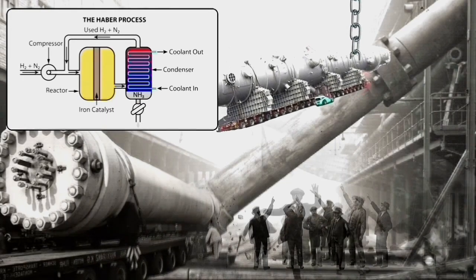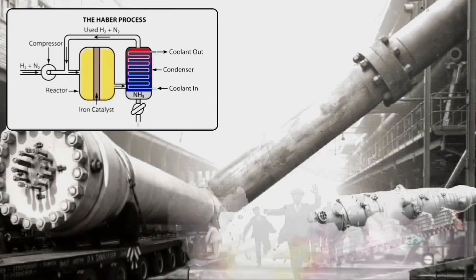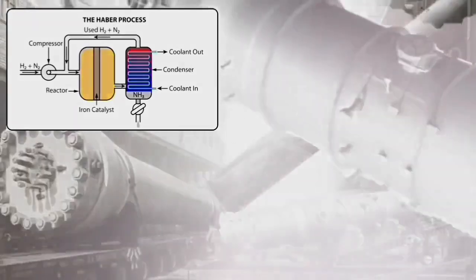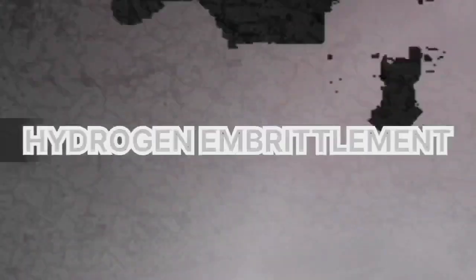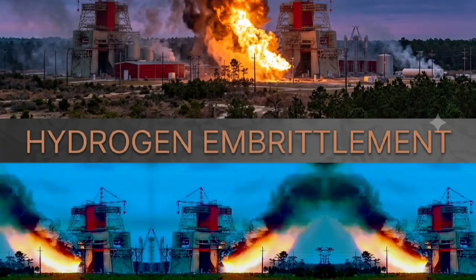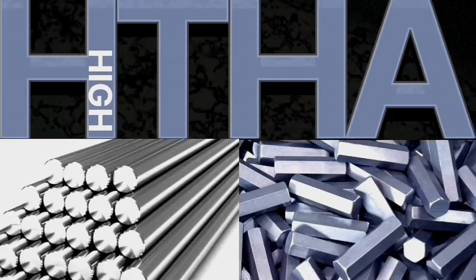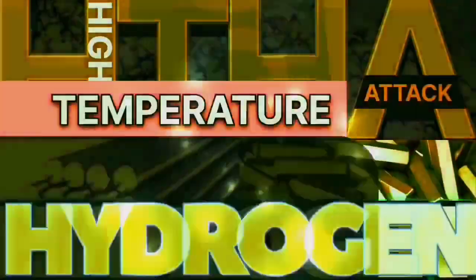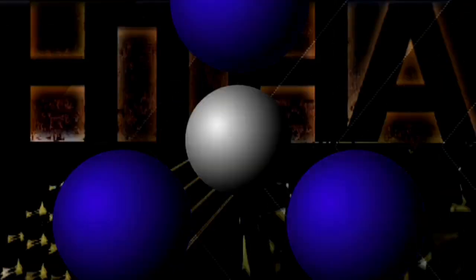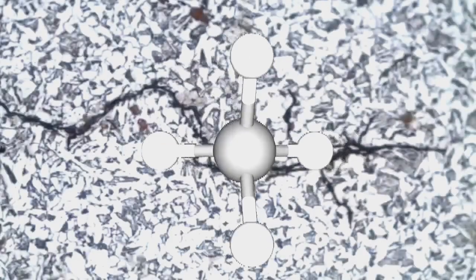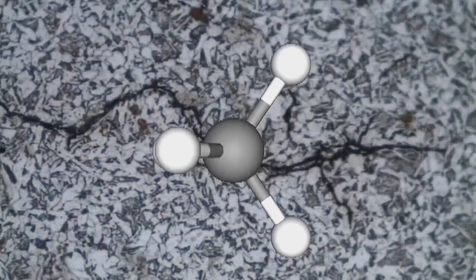One problem is that under these conditions, atomic hydrogen can diffuse into the steel. This can lead to hydrogen embrittlement and, at elevated temperatures, high-temperature hydrogen attack, displacing anything that's bonded to the carbon. If it can come in contact with 4 hydrogens, either via loose carbon or iron carbide, then it can form methane. Larger molecules cannot diffuse out easily. It accumulates at grain boundaries and within microscopic voids.